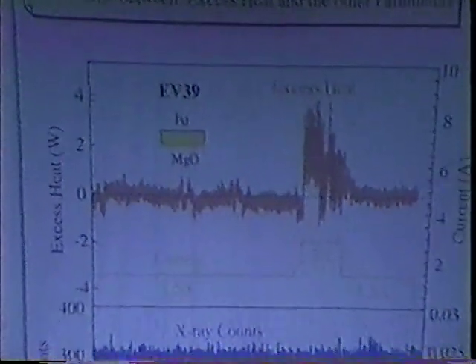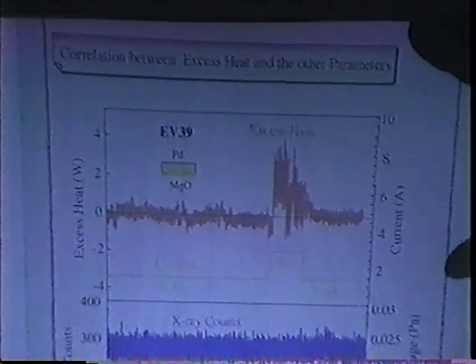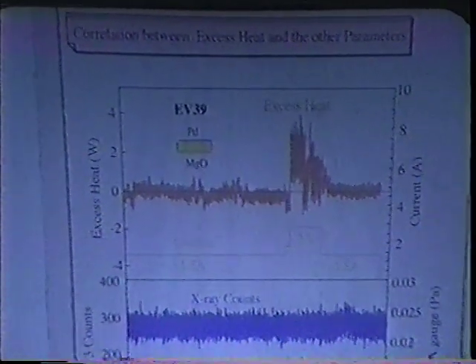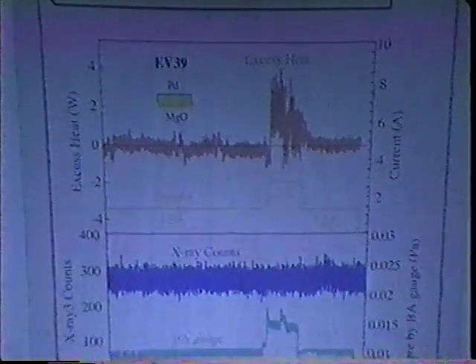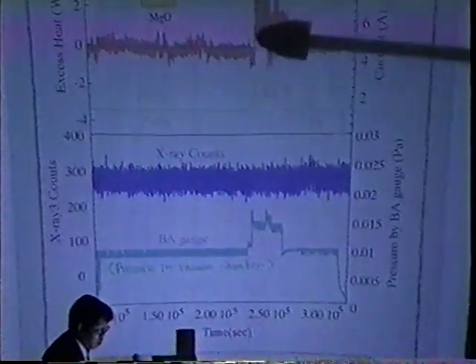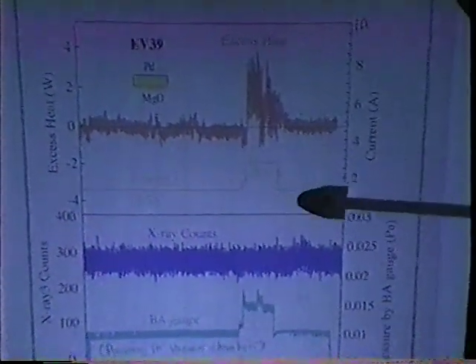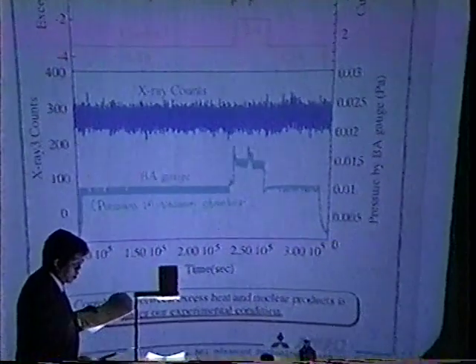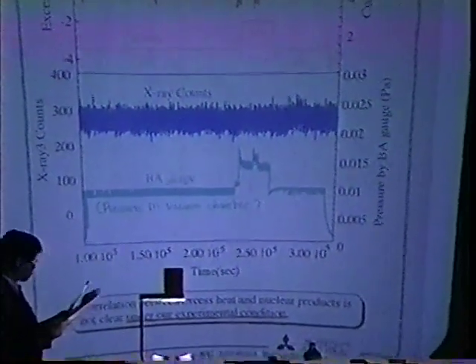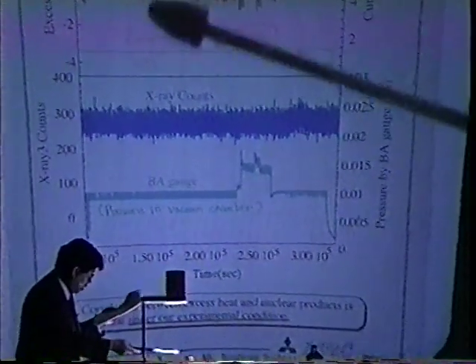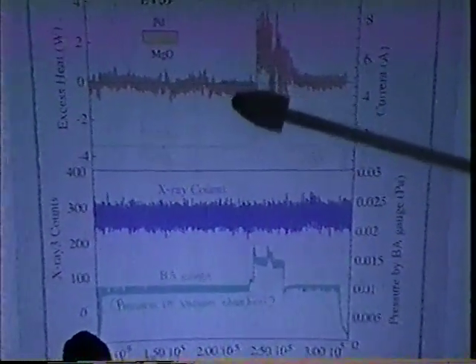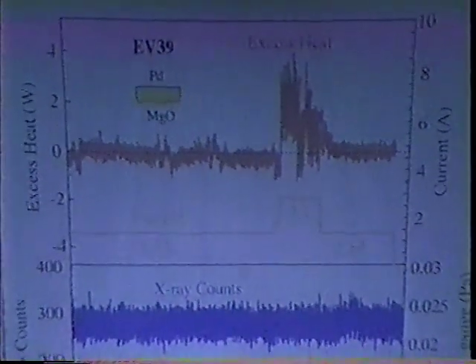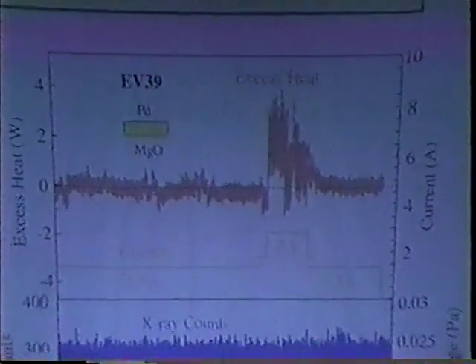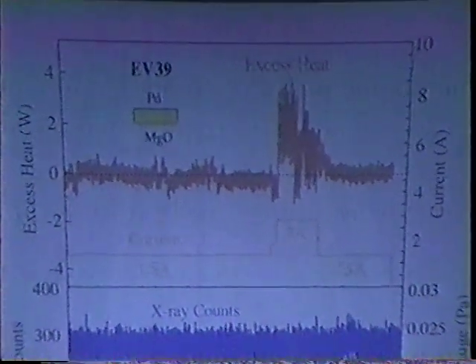Here is the view graph on correlation between excess heat and the other parameters. Horizontal axis means time, and the red line means the excess heat, and the orange line current, and blue the X-ray count, and green pressure in vacuum chamber. At low current, 1.5 ampere, we could not see any excess heat. After making up the current up to 3 ampere, which corresponds to the 1.5 ampere per square centimeter, excess heat generation was observed.